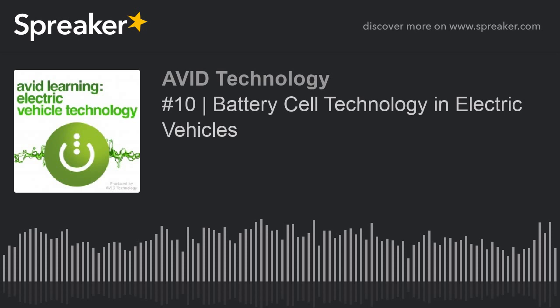So really, this has created at the moment two different categories of battery cell. We've got energy cells that are made from very, very thin materials and cell chemistries that are focused on energy density, but really at the expense of charge and discharge rates for the cells. And then we have power cells, which are typically used in hybrid cars or very high-performance vehicles, which use a thicker material to allow a higher charge and discharge rate, but typically at the expense of absolute energy density.